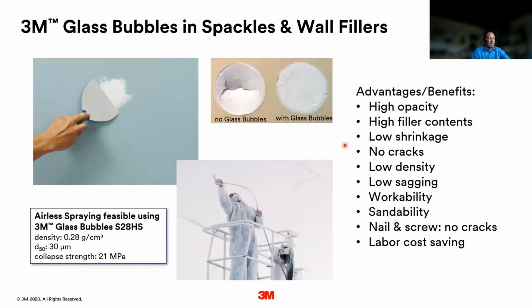The glass bubbles can be applied in wall fillers like shown here, but also in airless spackles that are applied to really larger areas. Here we have products like the S28HS, which are strong enough to survive the pressures that we see in airless spraying. This specific product, for instance, can stand more than 200 bars of pressure, and even after high pressure spraying with the airless gun, the bubbles do not break.